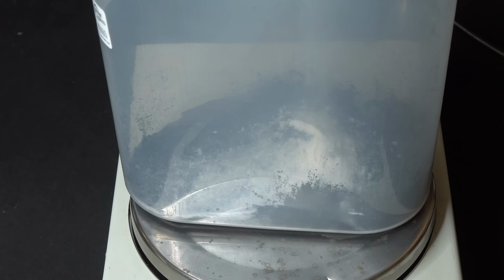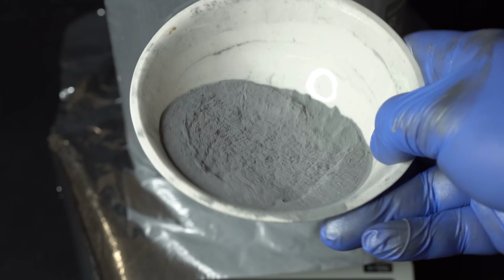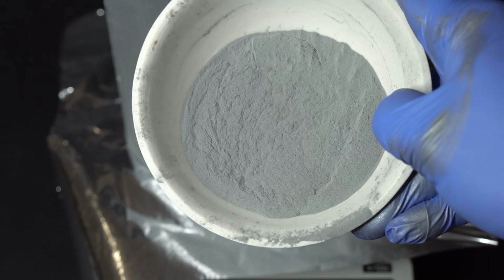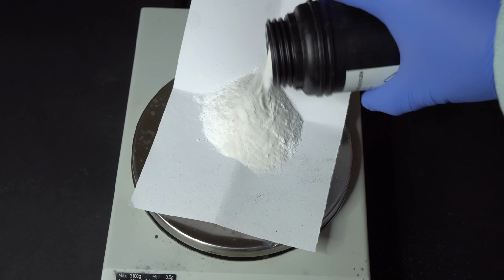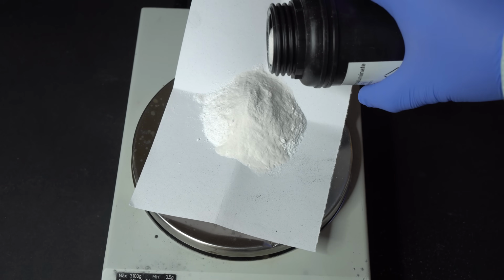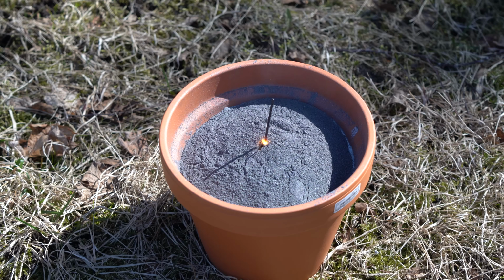For my second attempt, I mixed all the components using the same ratio, but I substituted the aluminum powder with a less fine aluminum powder and used less flux, reducing its amount to 30% of the whole mass, and stirred the mixture thoroughly. Hopefully everything will work out this time. Let's ignite it.